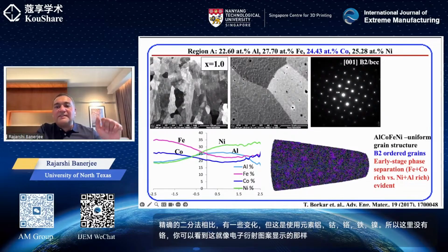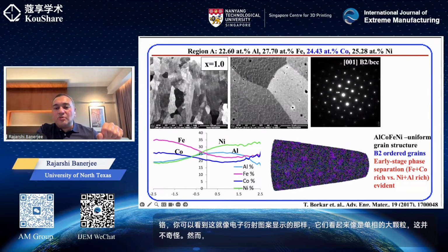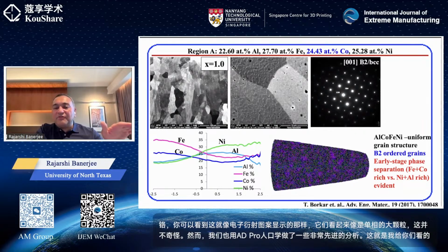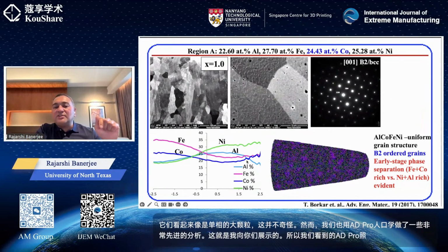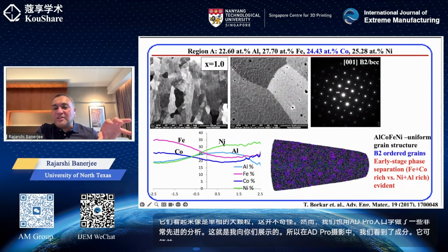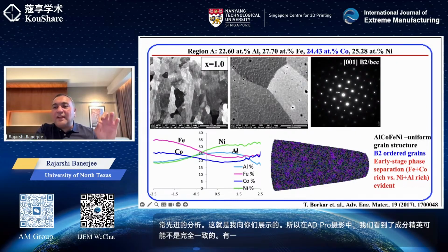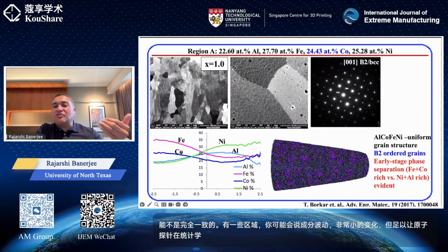No surprises there. However, we also do some very advanced analysis using atom probe tomography, and this is what I'm showing you here. In the atom probe tomography, we saw that compositionally, it may not be perfectly uniform. There are regions, or you might say compositional fluctuations, very small changes, but enough for the atom probe to statistically find that there are regions that are richer in nickel and aluminum and regions that are richer in iron and cobalt.